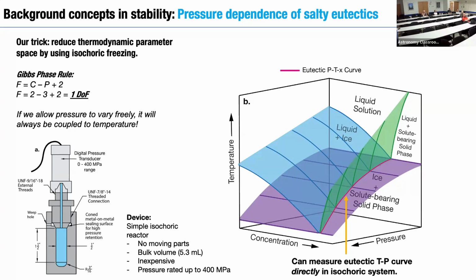So isochoric freezing gives us a way to directly measure this eutectic curve by taking a eutectic composition solution, putting it in an isochoric chamber, and simply cooling it down and melting it, right? Just changing its temperature, the equilibrium pressure that emerges based on the change of interior volume when phase change happens just comes out and we just have to read it, right? So now we can search this large three-dimensional parameter space by varying only one variable, temperature, and we can get this 1D spline, okay?